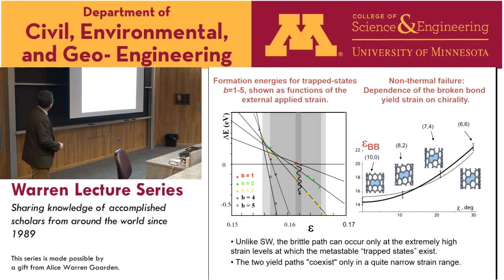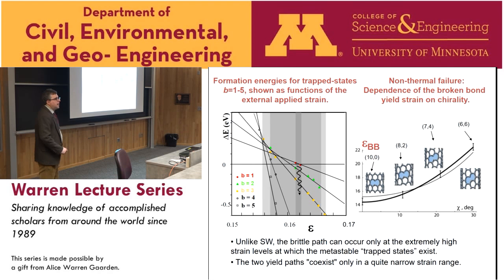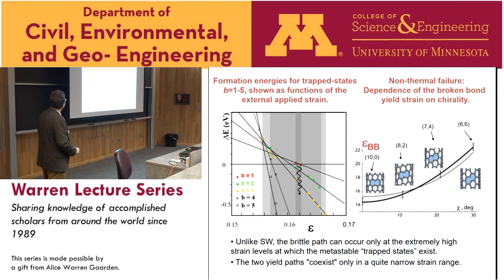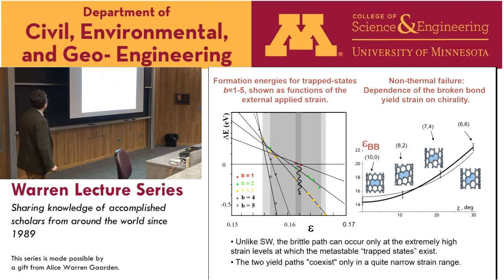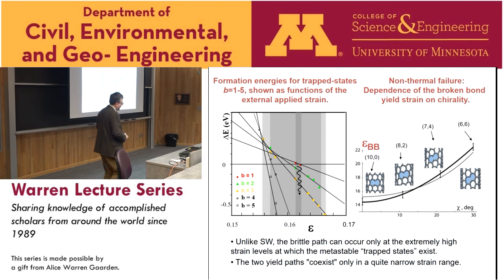This happens around 16% strain. What you see to the right is a picture of how this strain range at which the carbon nanotube breaks depends on the chirality angle. Tubes that are zigzag tubes — with bonds along the strain direction — fail earlier than the armchair ones, which have bonds oriented perpendicularly along the circumference. The breaking strain range depends strongly on chirality.